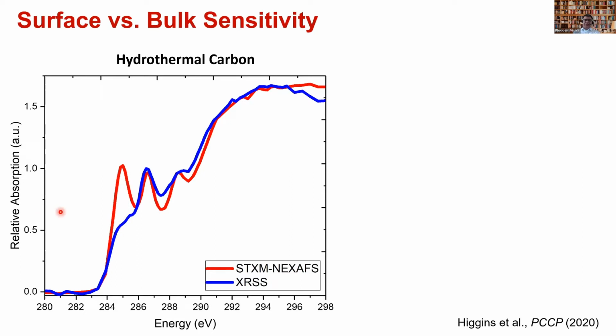But this was not a mistake. We repeated these measurements, and we actually even know what kind of peaks these are. So these measurements tell us that the surface is very different from the bulk, sort of corroborating some of our earlier experiments as well.